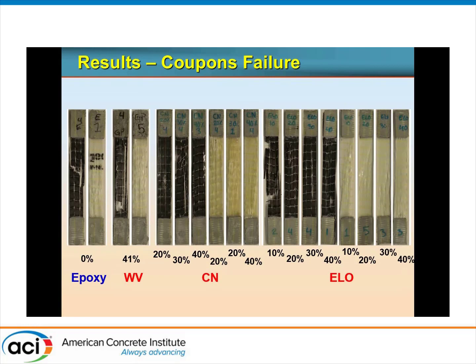One thing I should mention though is at the higher level of 40% in the second two types, the ELO and CN, the physical examination of the coupon was a little bit flexible. It was not as robust or rigid, if you will, as the lower percentage or the epoxy. And that's a physical sort of examination of the material itself.